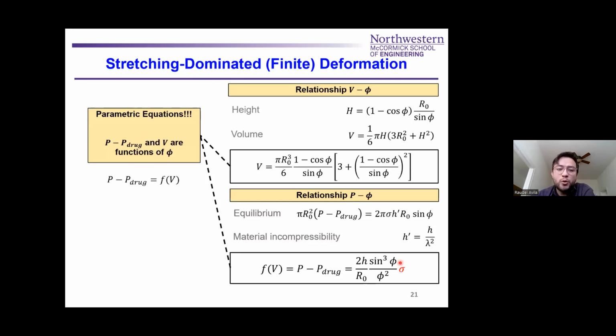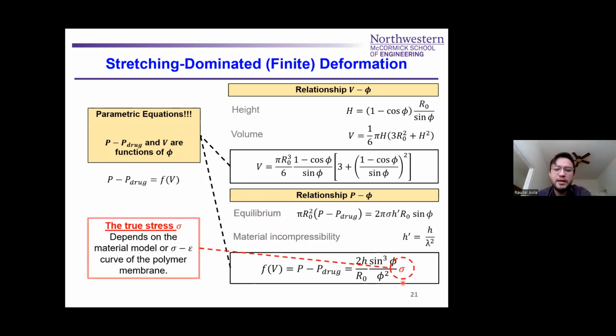Now, these two equations are parametric equations. They depend on the angle phi, but we can solve them simultaneously and plot them together, and we can obtain what our pressure versus volume function is going to be. And then from our pressure function, we have sigma, and this sigma is going to be the true stress. The true stress depends on the material model or the stress-strain relationship curve of your polymer membrane.